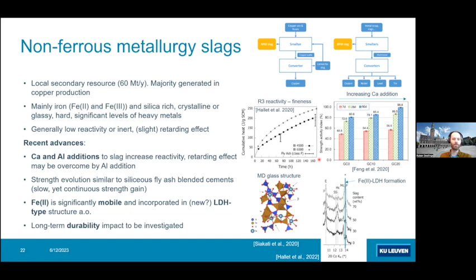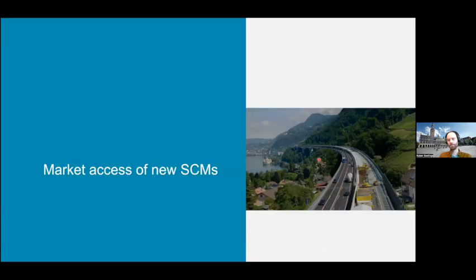this is beneficial. What is interesting to see is this chemistry is quite different. It's mainly iron and silica, and iron 2, divalent iron, seems to be mobile in the reactions and can be incorporated in a new type of layered double hydroxide. That's a bit like an AFm structure, amongst others. What we still definitely need to have more information on is the long-term durability impact.